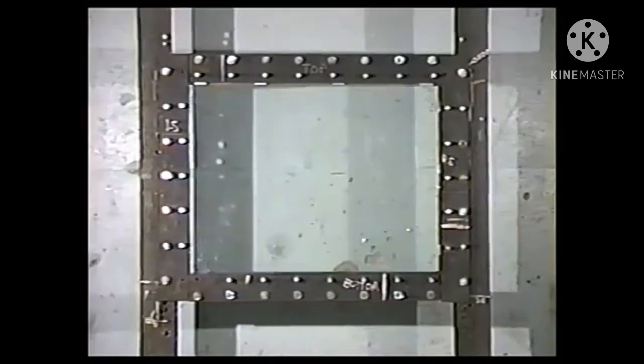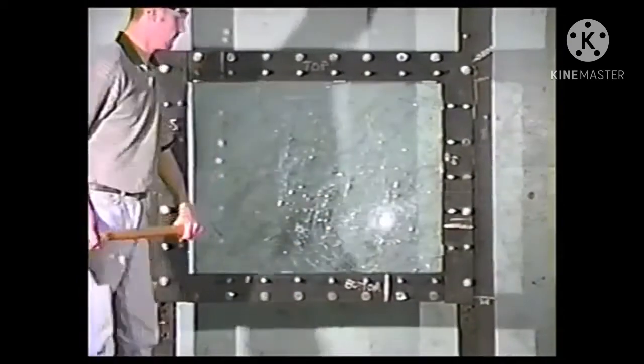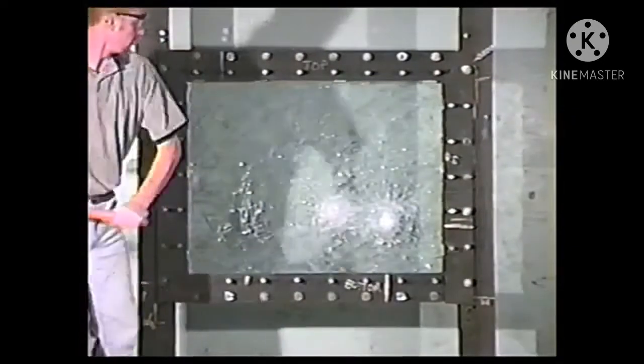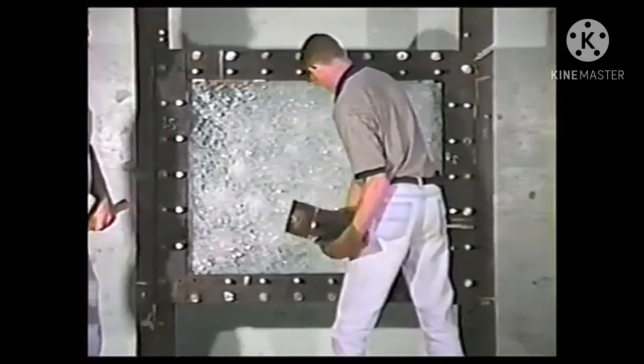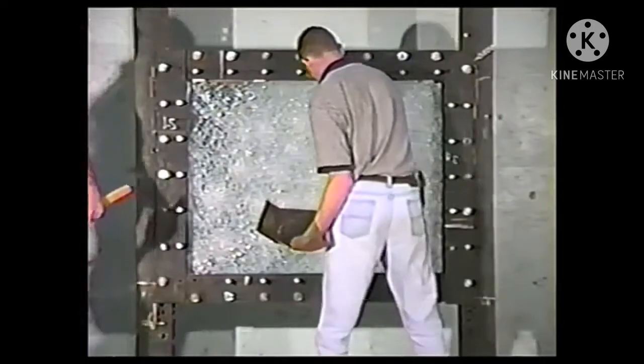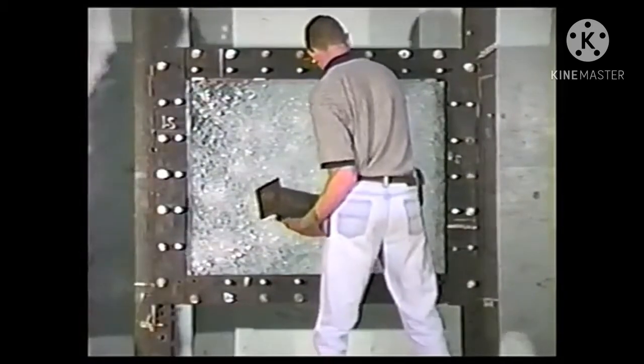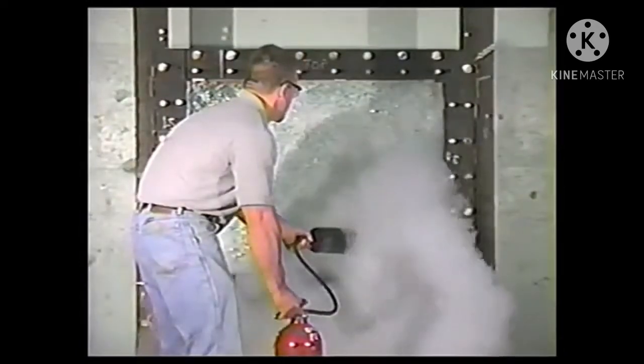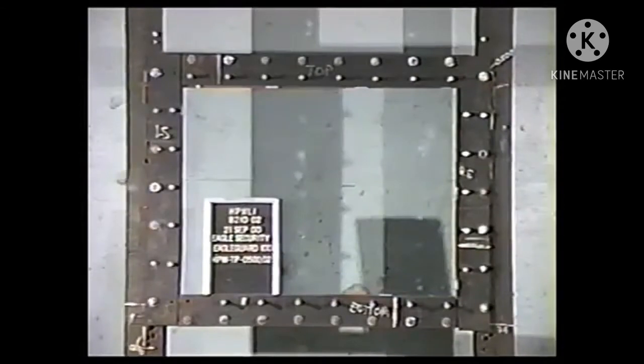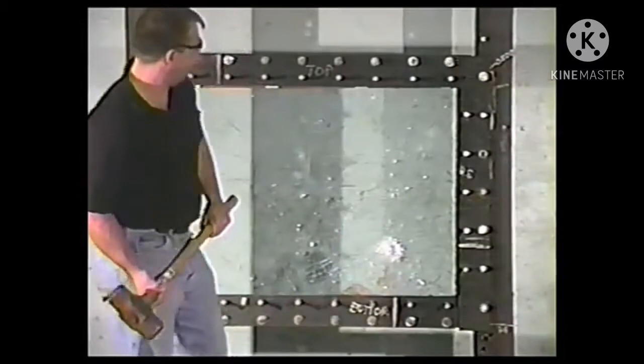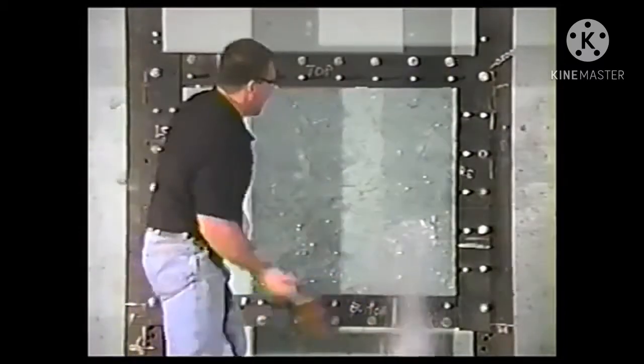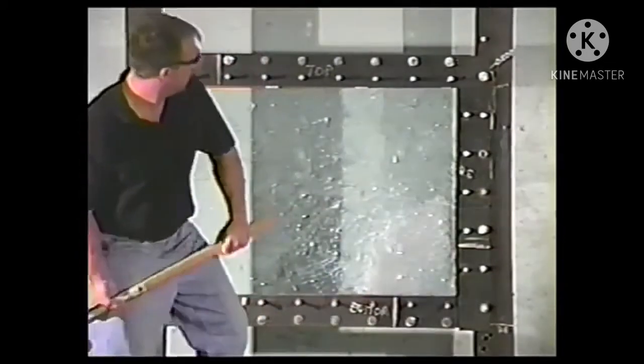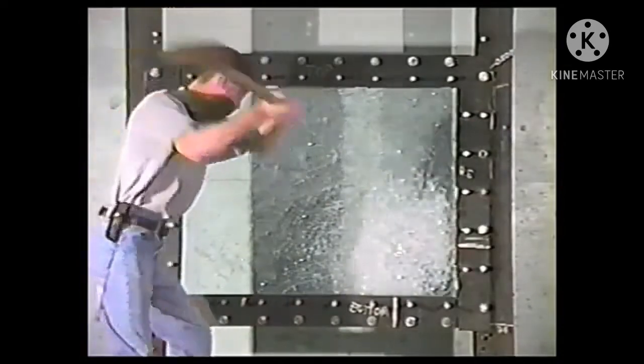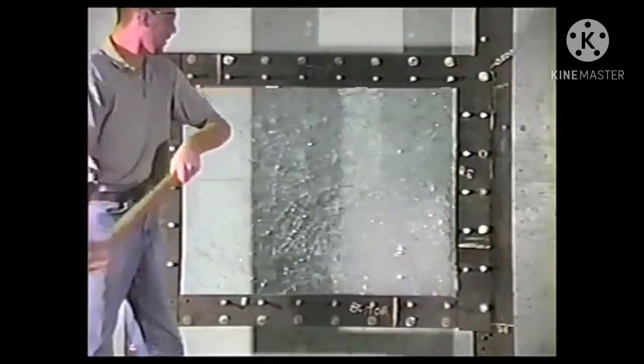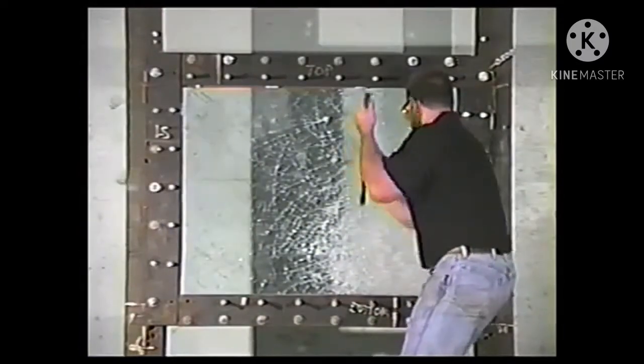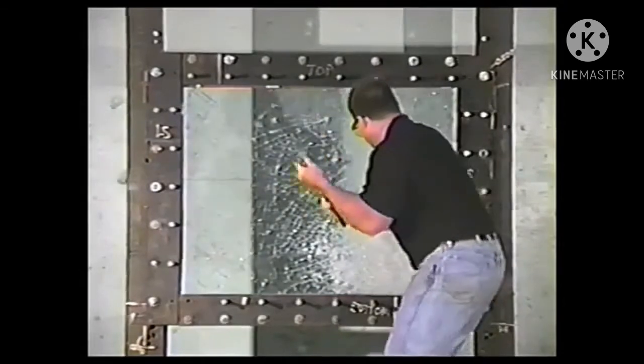Bendheim's decorative high safety glass is produced by using liquid resin and PVB laminates under very controlled conditions. There are two levels of impact-resistant high safety glasses available. Level 1 high safety glass is usually made up of 5/8 inch glass-clad polycarbonate. It takes about 30 minutes for a perpetrator to gain entry. Level 1 glass effectively stops .22 caliber and .38 special bullets. Level 2 high safety glass is often made up of 3/4 inch glass-clad polycarbonate. It takes about 1 hour to penetrate, and in addition to the bullet types already mentioned, Level 2 glass also stops .357 Magnum bullets. Additional layers of glass can also be added to create a unique design. Because annealed glass is used, we can water jet cut to size if needed. A clear edge, tempered, or heat-strengthened glass is also available.